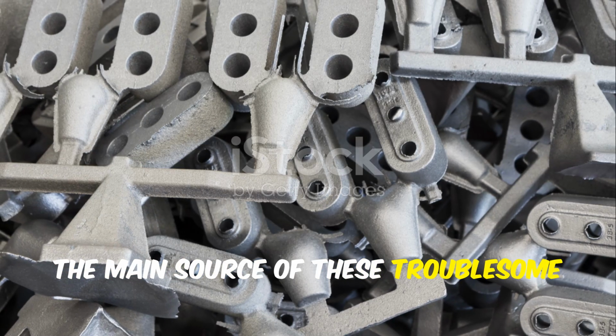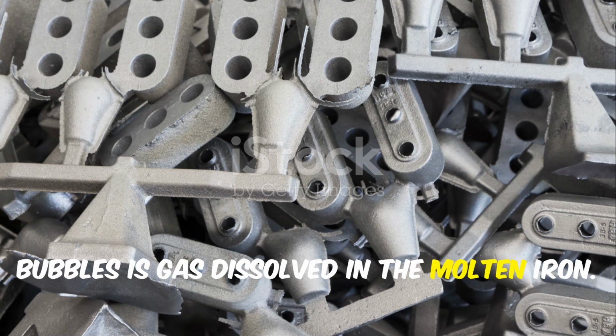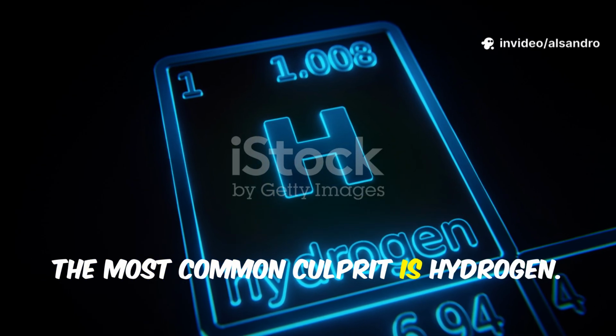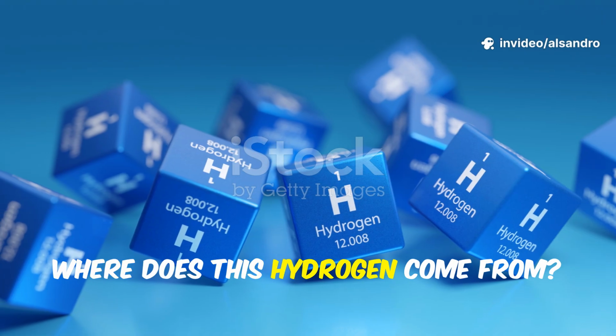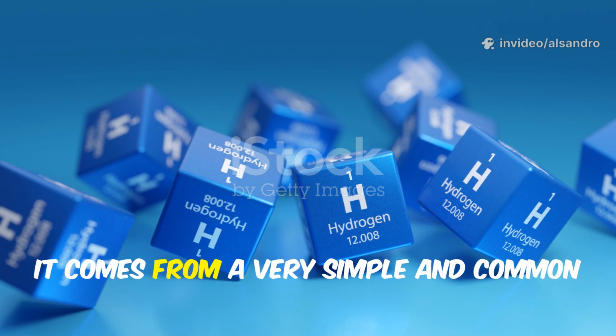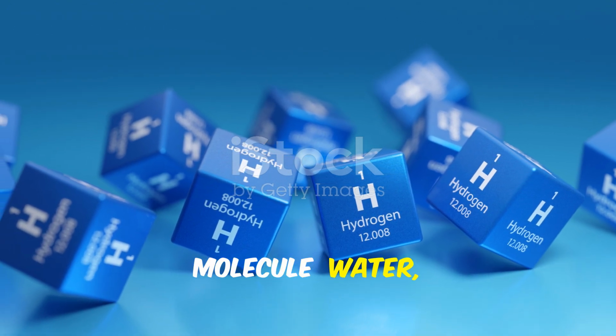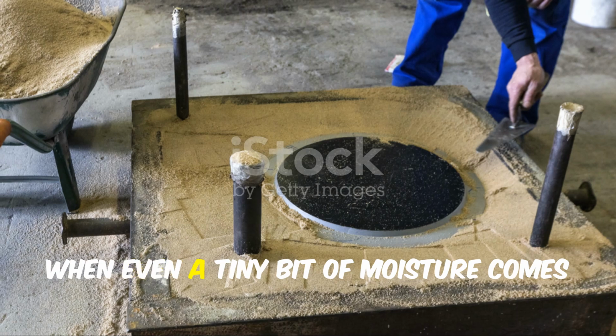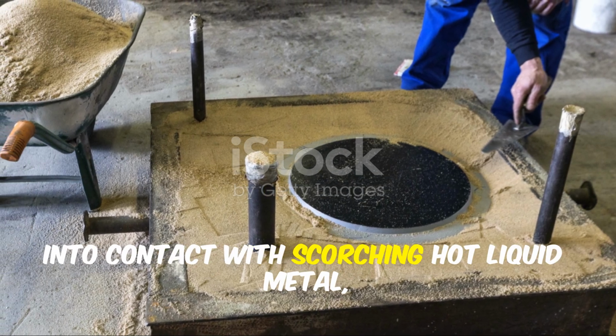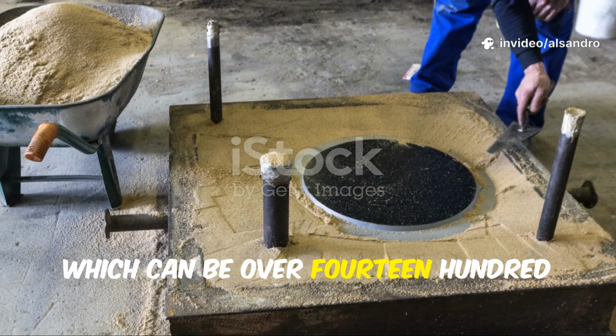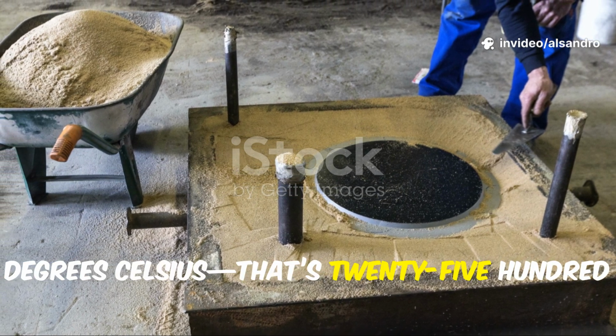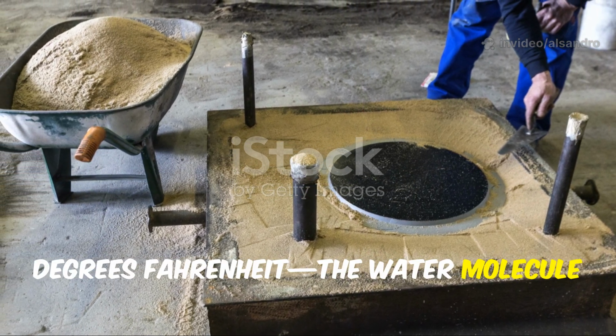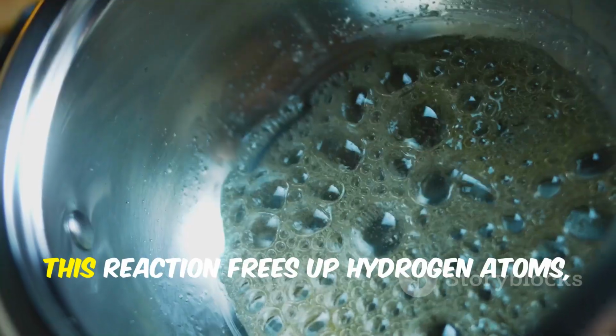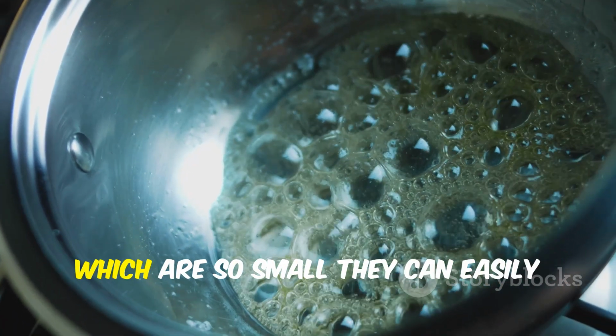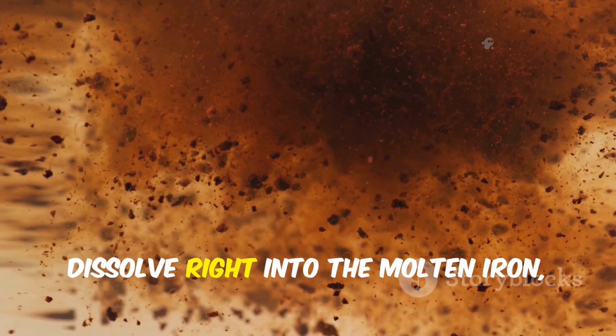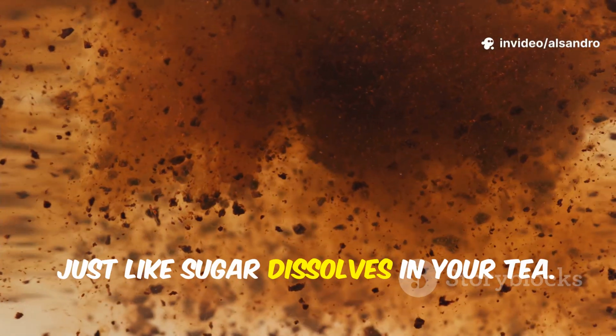The main source of these troublesome bubbles is gas dissolved in the molten iron. The most common culprit is hydrogen. Where does this hydrogen come from? Often, it comes from a very simple and common molecule, water, or H2O. When even a tiny bit of moisture comes into contact with scorching hot liquid metal, which can be over 1400 degrees Celsius, that's 2500 degrees Fahrenheit, the water molecule violently splits apart. This reaction frees up hydrogen atoms, which are so small they can easily dissolve right into the molten iron, just like sugar dissolves in your tea.